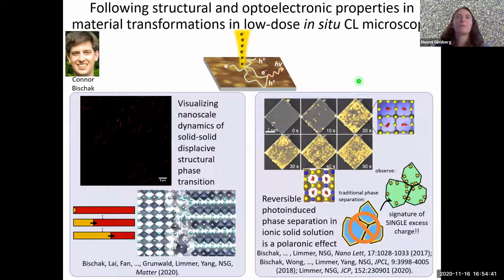Okay, so we've been working over the years to extend the applicability of cathodoluminescence microscopy, so basically mapping the light emission in a scanning electron microscope. So extending this applicability to soft materials to not only image their optical properties at the nanoscale, but to follow their dynamics non-invasively, essentially by doing things like increasing light collection efficiency and substantially lowering the electron dose. So these two examples I'll show are emblematic of what we can do.